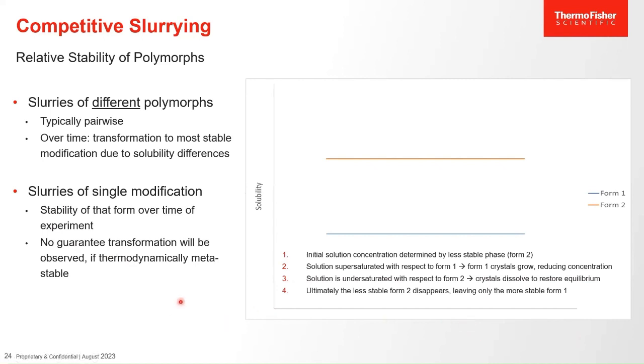So finally, let's talk a little bit about competitive slurrying. Competitive slurrying is one method of determining relative stability of polymorphs, and it is the only experimental method, without going into deep thermodynamics, that easily allows you to distinguish the relative stability of polymorphs. How is it carried out? It is typically an experiment where you slurry at least 2 polymorphs, so it's typically carried out pairwise, but there's nothing to stop you from slurrying several polymorphs. And you take saturated slurries of both polymorphs, you mix them, you stir them for a period of time, and at the end, only the most stable polymorph remains.